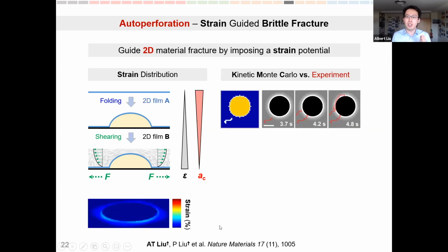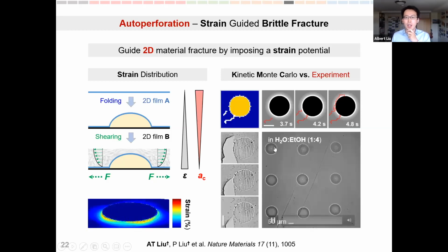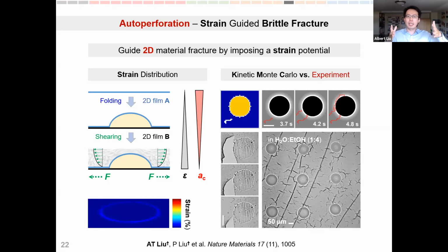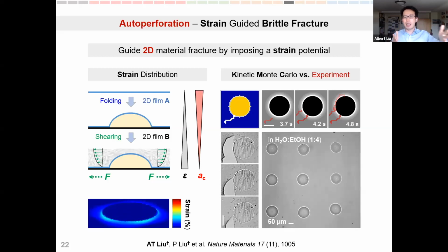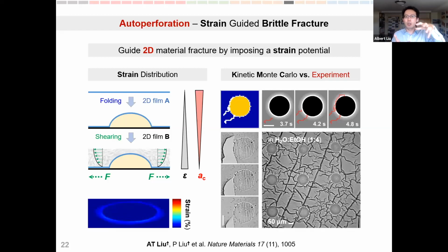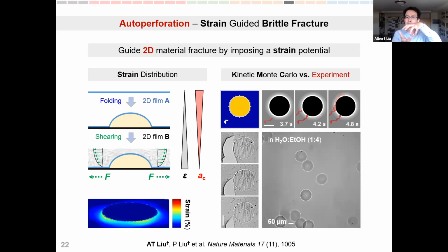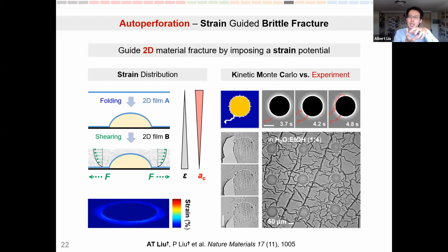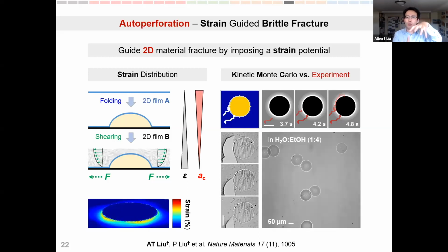So according to Griffith's theory, a randomly generated crack will get arrested by this ring of maximum hoop strain, and it will actually cut along the edge of this polymeric pillar that we define using our inkjet printing. And experimentally, this happens basically exactly as what we have predicted. These particles will get cut around the edges, and the 2D material will only survive at locations where it encapsulates the particle. And as a result, when the particle gets lifted off, it has a perfect encapsulation by two layers of 2D material, one on top, one on bottom, and it can travel around as a colloidal particle.